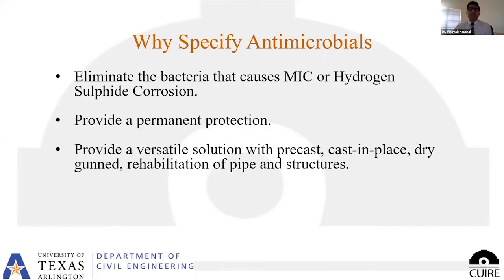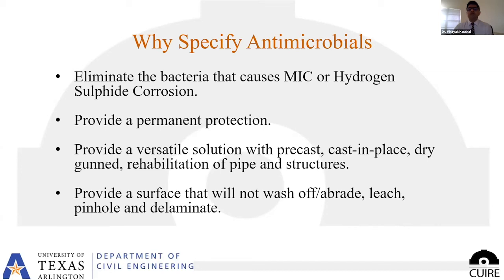So in addition to this, there is also need to specify antimicrobials. So why do we do that? It is to eliminate the bacteria that causes MIC or hydrogen sulfide corrosion, to provide a permanent relief from this issue and protect the structures, and also to provide a versatile solution with the precast, cast in place, dry gunite, and rehabilitation of pipe and structures, and also to provide a surface that will not wash off or abrade or leach and pinhole, and also to eliminate the delamination, etc.